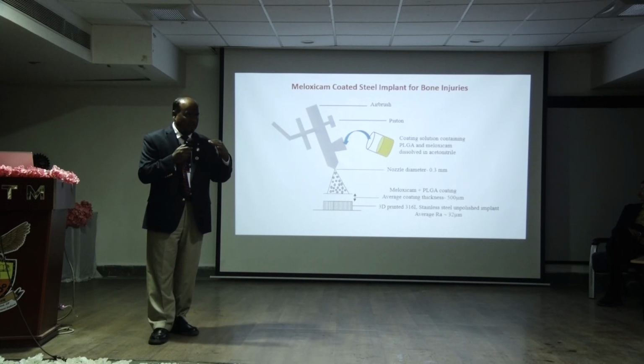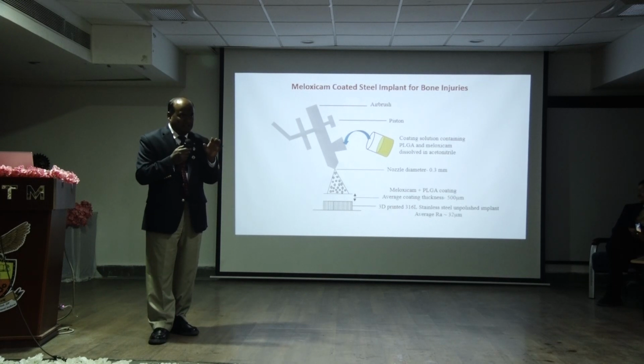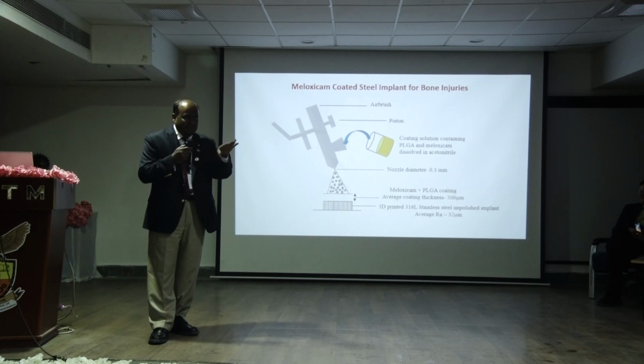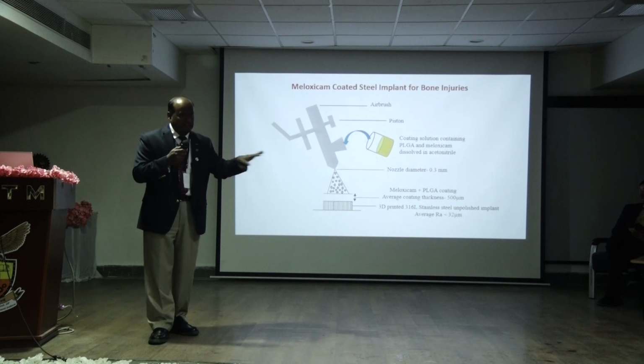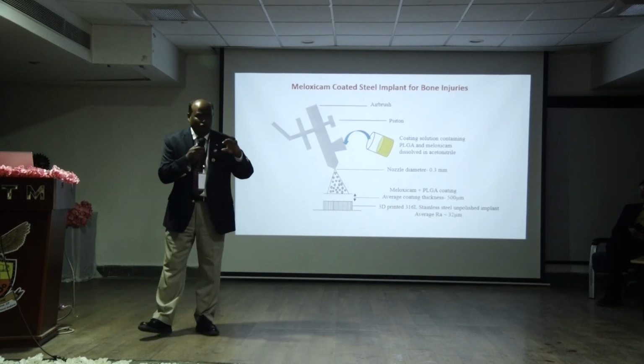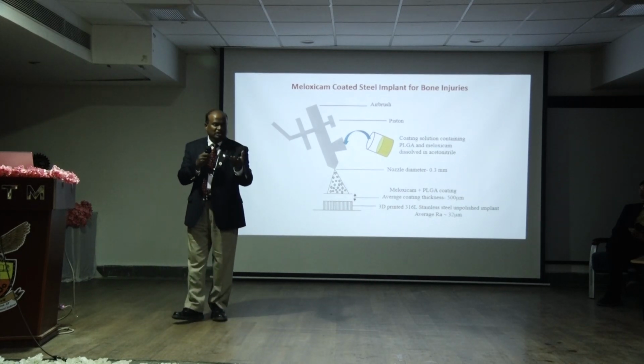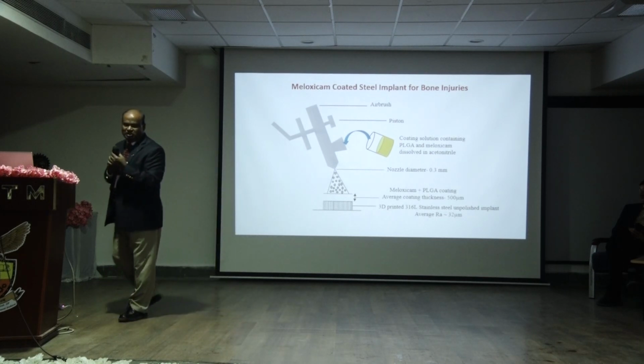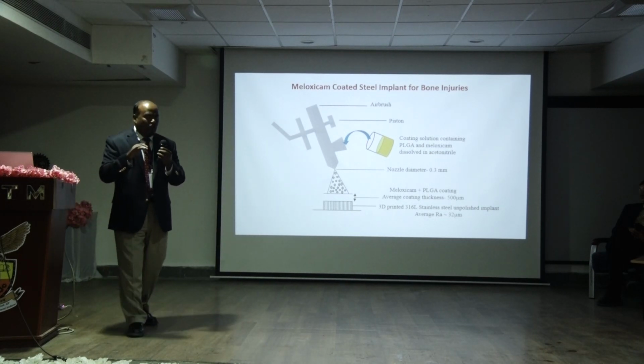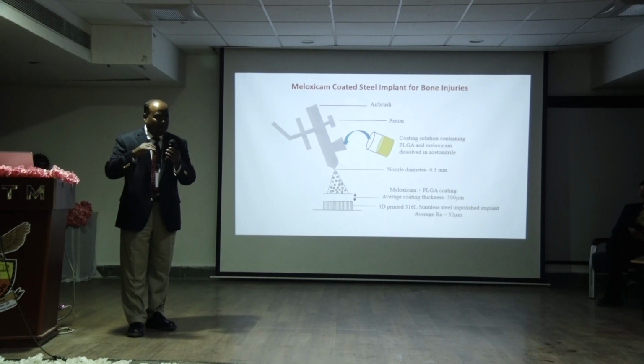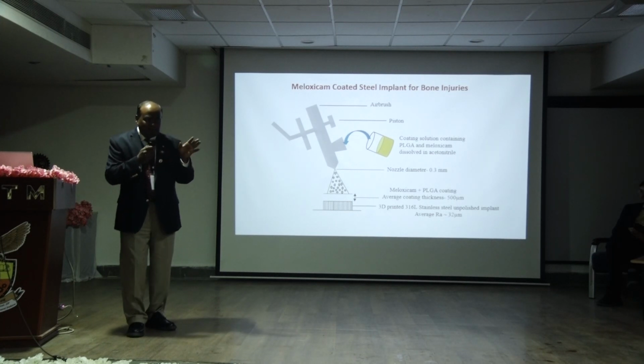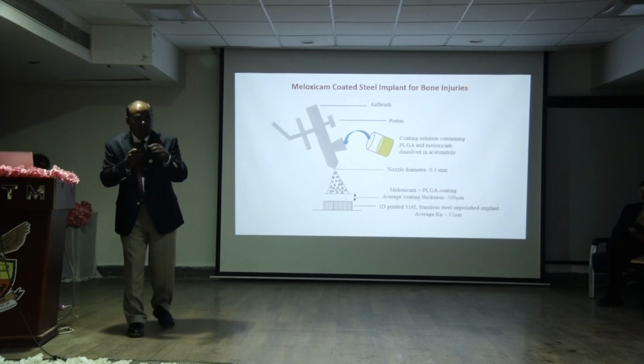That is the indication that actually visually you will not be able to even see that the drug is deposited. So only way we know that the drug is there or not is to measure the surface roughness. That is the reason we measure the surface roughness to know that the drug is deposited. Of course, we also look at the weight gain of the implant because these are irregular structures. There is no way you can deposit the drugs uniformly. So that's why we measure the surface roughness to know that the drug is deposited uniformly onto the surface.